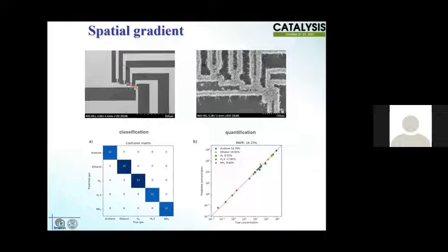That means at different, obviously, lower and lower temperatures. Here you see the same structure with the heater and 1, 2, 3, 4 sensors once the nanowires are grown. And here you can appreciate why this system can be 0.2 of a millimeter, because it uses only one material. If we wanted to put different materials, it's really, really difficult.